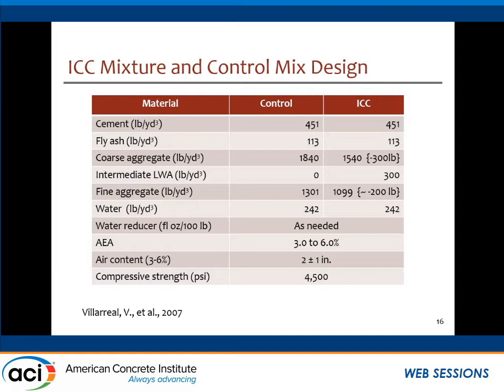So here's an example of an internally cured concrete mix design, and this is specifically the mix design that was used at the Intermodal facility. We got this data from Victor's paper. There's the control mix and the ICC. You have the same amount of cement, same amount of fly ash. You have 1840 pounds of coarse aggregate in the control mix, and you've taken off 300 pounds for the ICC mix. Now, you've introduced intermediate lightweight aggregates, 300 pounds here. And fine aggregates, you've again reduced by about 200 pounds.